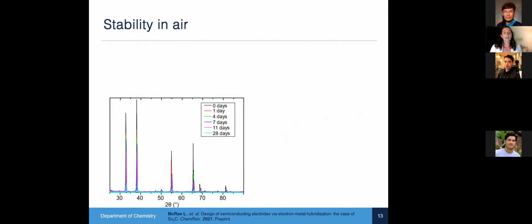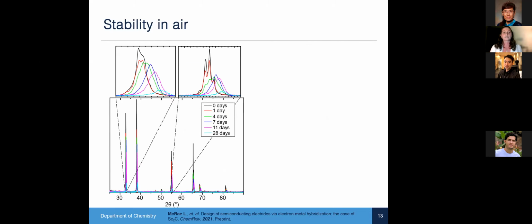So we did this by doing XRD of the product after sitting in ambient conditions for a set period of time. We did this over a month and took diffraction patterns at various time points. We found that as the product sat in air, the crystallinity of the peaks decreased, and we end up getting much less intensity, much broader peaks, indicating that it's forming an amorphous phase.